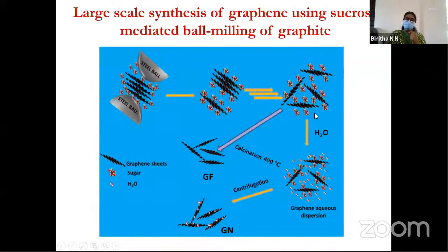We have tried this method for the large scale synthesis of graphene, and our milling agent is low cost sucrose. Here, graphite is mixed with the sucrose first, and then it undergoes ball milling, and the ball mill mixture upon calcination leads to graphene. This is hydrophilic graphene.